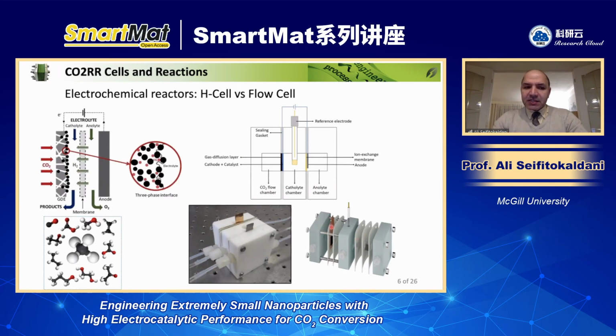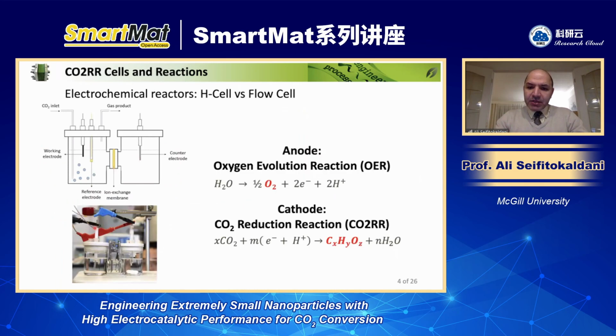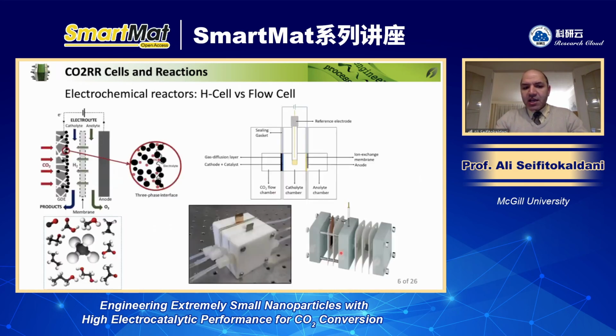Usually we use a copper-based catalyst because it's, I would say, so far the only transition metal catalyst which is able to convert CO2 into different hydrocarbons. The other metals either produce just CO, carbon monoxide, or formate, formic acid, depending on the electrolyte. So we use mostly copper-based catalysts, and for the anode side, if that's the oxygen evolution reaction, we use nickel-based or platinum-based catalysts. When we have the reaction, either using the H-cell or the flow cell system, you may produce a bunch of different products as already mentioned: carbon monoxide, formate, methane, ethylene, ethanol, propanol, so many different products. And that can be an opportunity, but at the same time, it could also be a challenge.